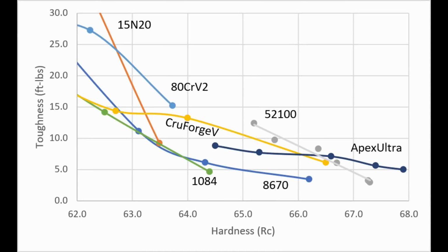So I think once you go beyond about 61 Rockwell, it makes more sense to move to a higher carbon steel. And so I have some options here. Even 80CrV2, you can temper it down to like 63.5 Rockwell and still maintain pretty good toughness. But you can also move up to 1% carbon steels like Cruforge V or 52100, and they can be heat treated to 64 plus RC without their toughness really falling off.